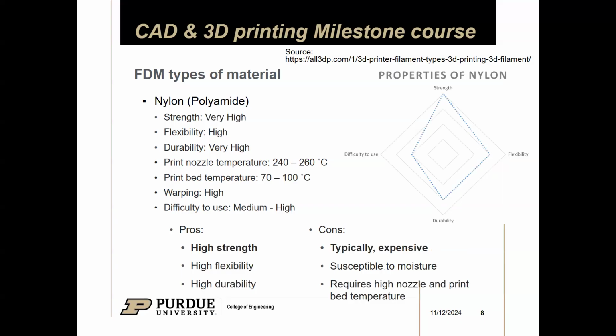With nylon, we're starting to approach the quote unquote engineering grade materials, mostly because they're harder and harder to print. Pure nylon is extremely hydrophilic, similar to PETG, but a lot worse, to the point that people recommend you print out of an active dryer, right? So for PETG, you can dry it, leave it out for a little bit and print it, but nylon is so susceptible to moisture that it can absorb enough while you're printing that it can affect the print. So if you're printing nylon, print with a dry box or something, keep it nice and dry.